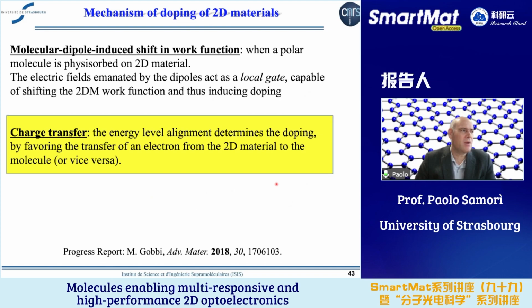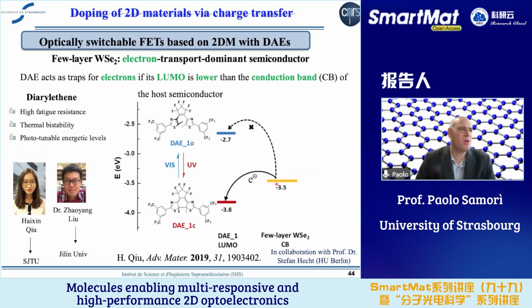Now, what I'm going to show you now is that you can also use another doping mechanism, which is the charge transfer. And this is about energy level alignment that determines the doping by favoring the electron transfer from the 2D material to the molecule and vice versa.